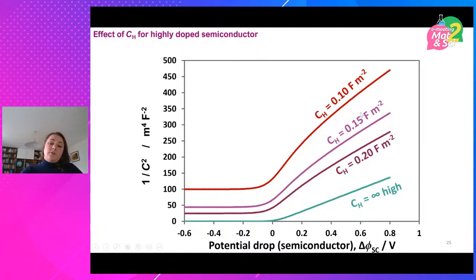And then you have some of the published values. So you can see that for a highly doped semiconductor, the actual resultant Mott-Schottky plot looks very different. And actually, these look a fair bit more like what you actually see in publications. Now, it's rare to actually have a complete Mott-Schottky plot over such a huge potential range. So normally you get some sort of linear plot over a small potential range and you extrapolate.